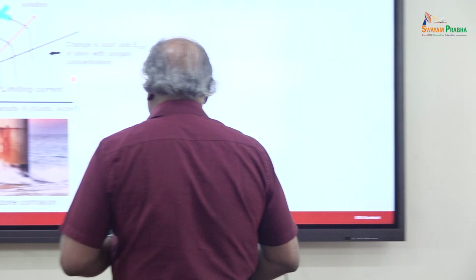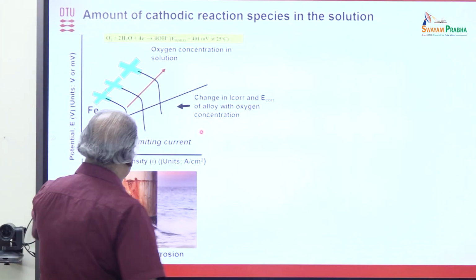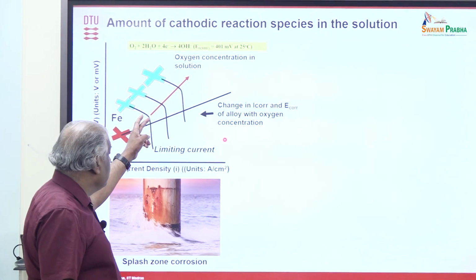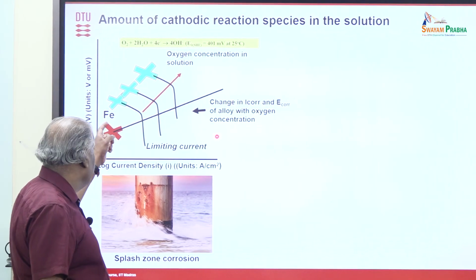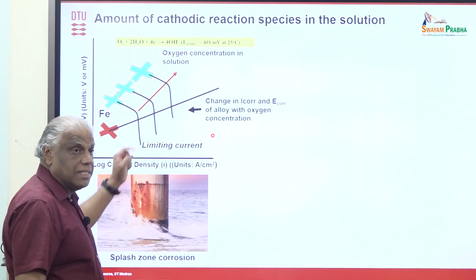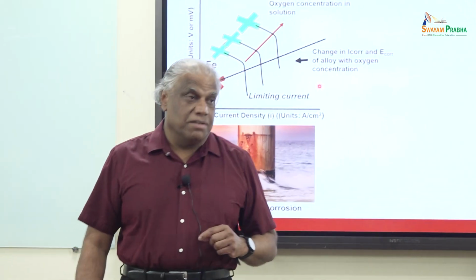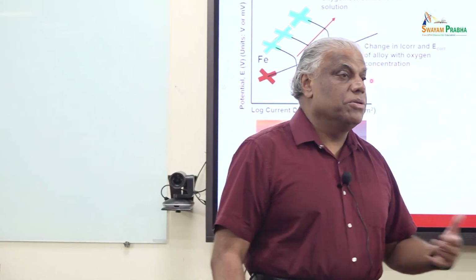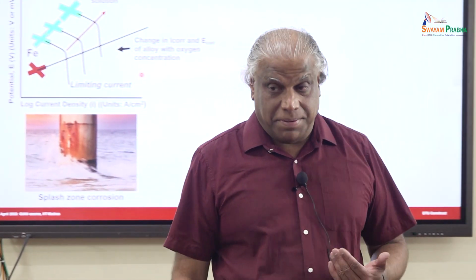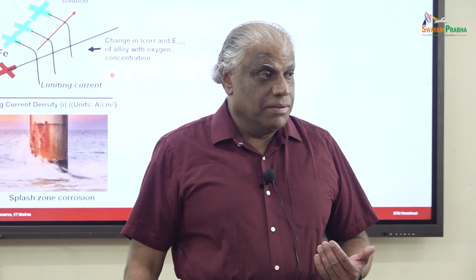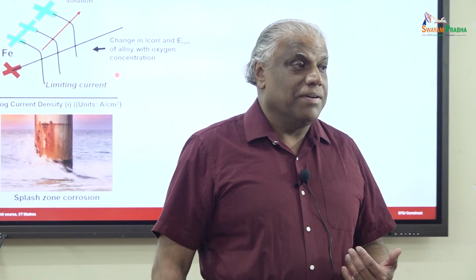It will not be able to keep the concentration that is needed. So that means that at one time you get a net depletion of oxygen on the surface, and then you cannot increase the current more than that. Even if you increase the potential, you will not change the current, and you will reach a limiting current value depending on the amount of oxygen in the solution. This is what happens. So that's why we draw the curve like that.